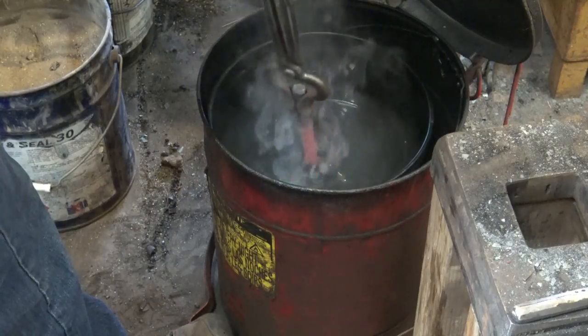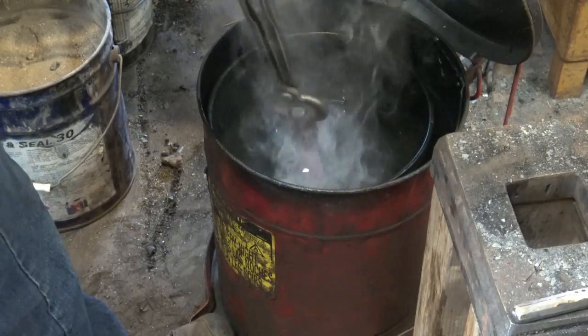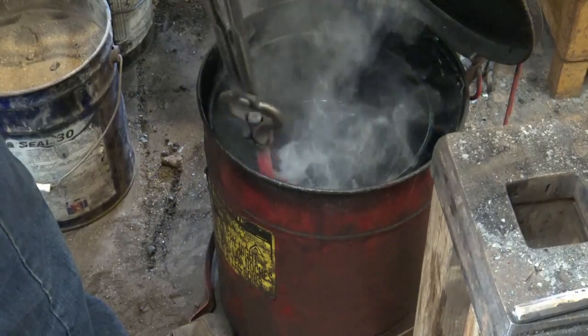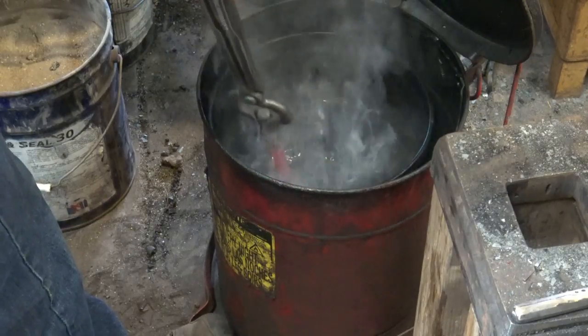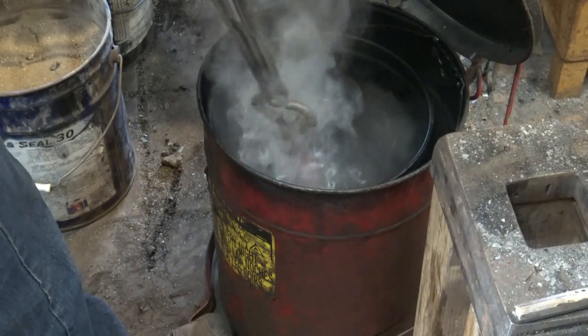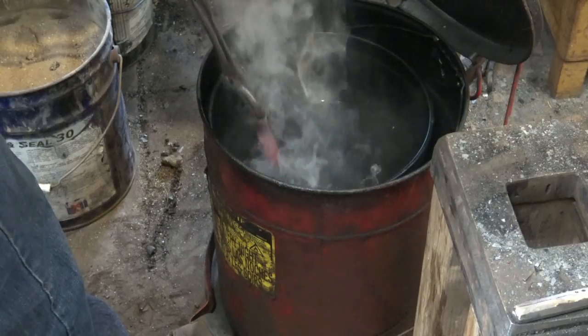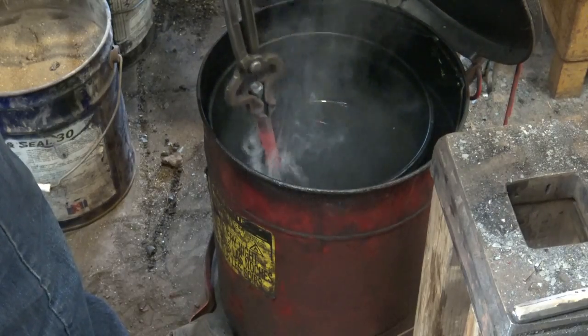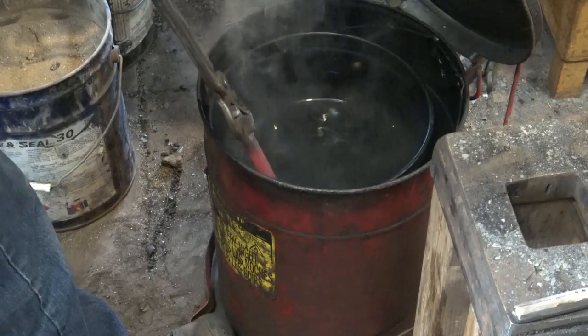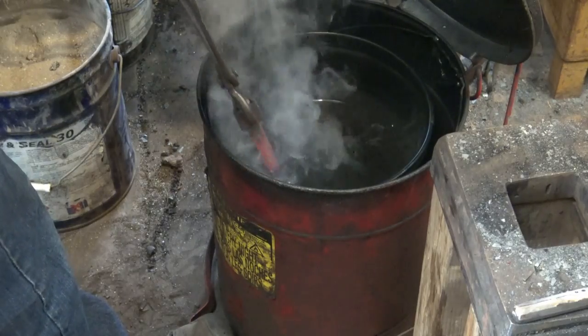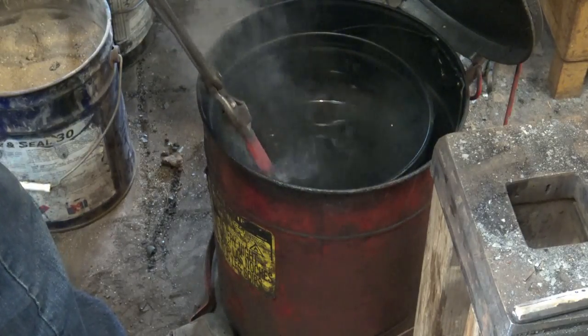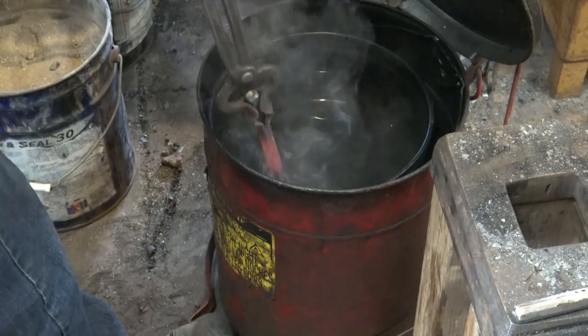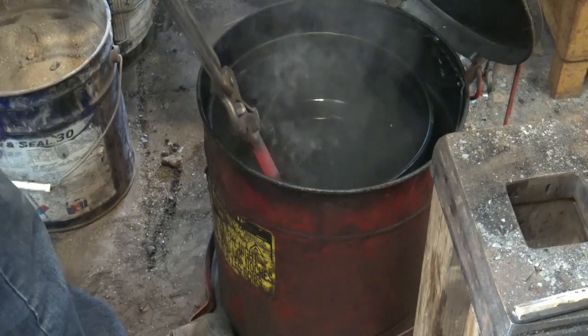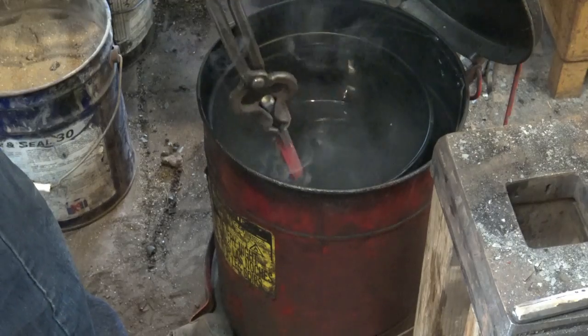You want to make sure it's completely cooled and move it up and down a little bit so you don't have a stress line right at the cold and hot mark there. It's okay to quench the entire tool if you're going to temper this in an oven. You don't have to quench only the end. This is just the old blacksmith's way of doing things.